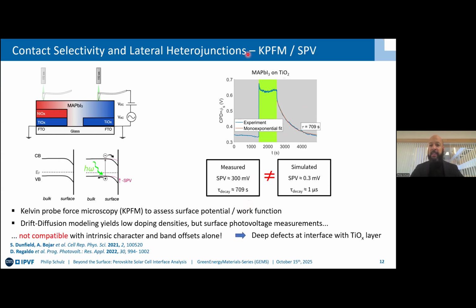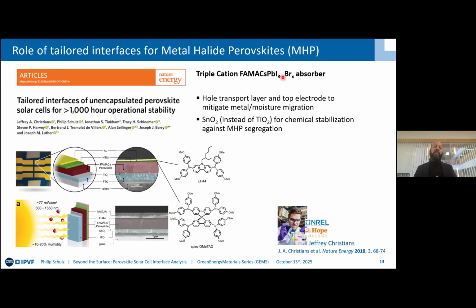In this case here with the titanium oxide layers, this is MHP on top of titanium oxide. That would lead to trap and release events, for instance, for this long decay. And indeed, there were additional indications that these defective interfaces play a role not just for performance, but also for stability. And I wanted to briefly home in on this issue in some earlier work that we published a while ago, where it was really key to enhance the perovskite solar cell stability, even for an unencapsulated device